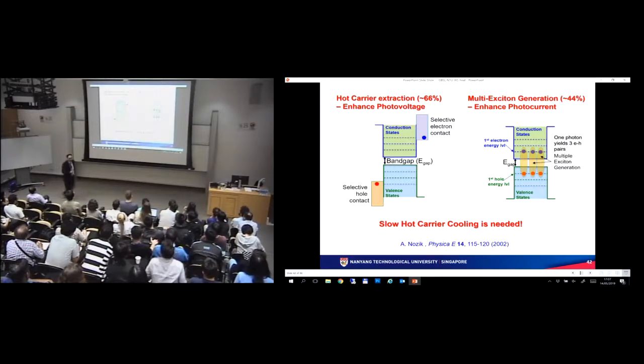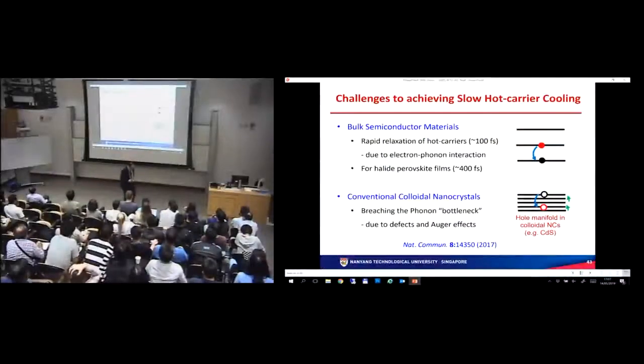Now, what's the problem with traditional semiconductors? In typical semiconductors, the bands are closely spaced, especially for bulk semiconductors. You have very rapid relaxation of your hot carriers, typically on the order of hundreds of femtoseconds. And just for comparison, for the halide perovskite films, which I showed earlier, it's a bit slower, around 400 femtoseconds.